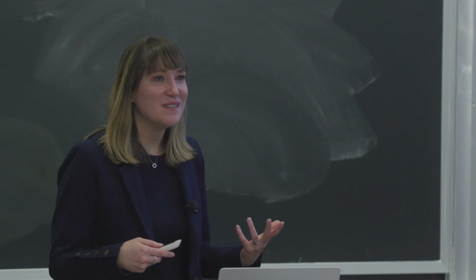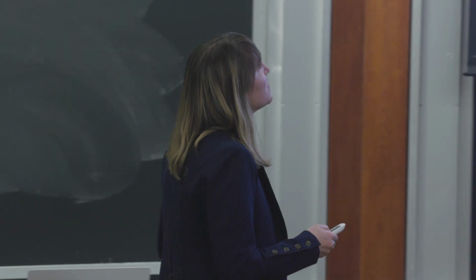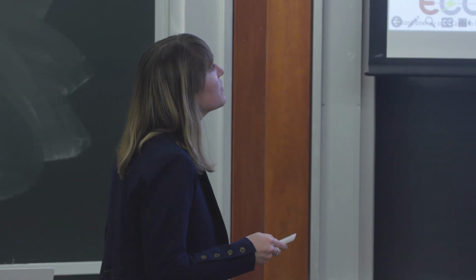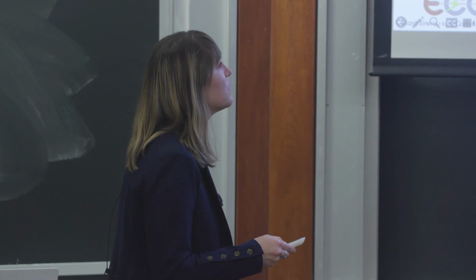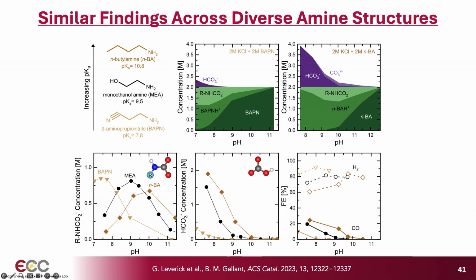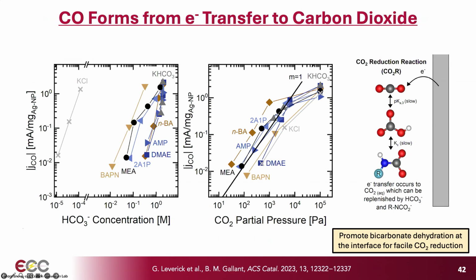We looked at many more amine systems of diverse structures and different pKa values, and we generally found the same. So this appears to be universal. So increasing CO selectivity correlates with decreasing pH, which correlates with increasing bicarbonate concentration, but not carbamate. Okay? So this suggests to us that the efficiency is really tracking with the bicarbonate concentration. And you might think that that's kind of tied up and all said and done. But it's not quite so simple.